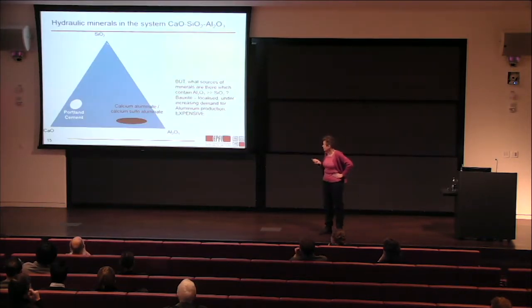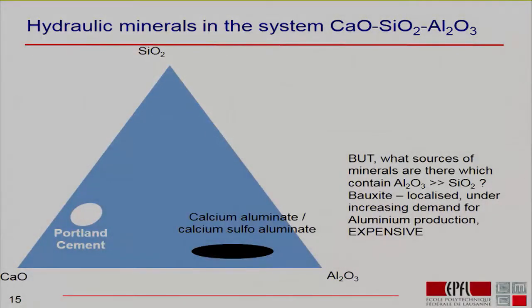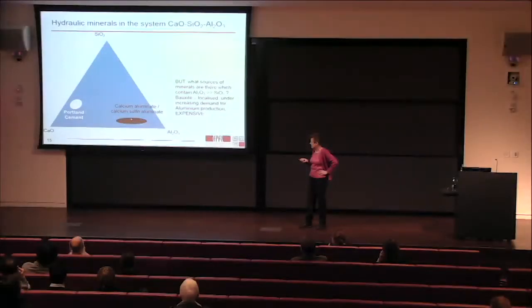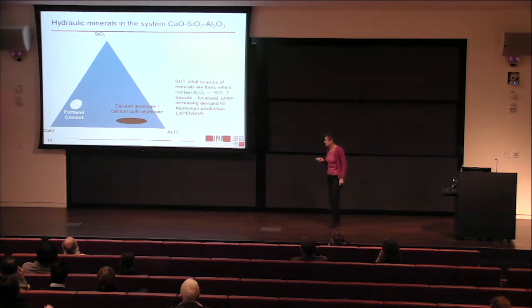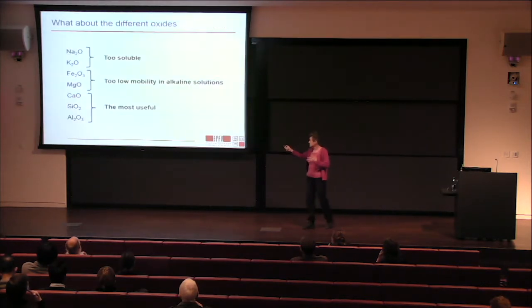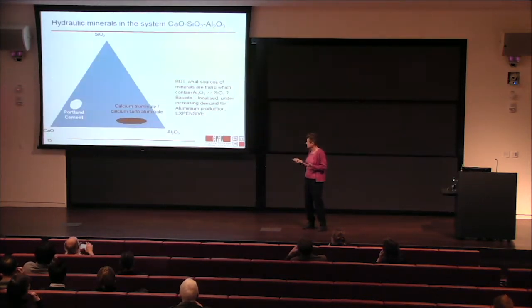And here, if we look at this system, calcium, alumina, silica, we see we've got the composition of Portland cements here, which are basically calcium silicates. The only other hydraulically reactive minerals we have in this system are down here, and this is basically calcium aluminate cements, and by extension, with a bit of sulfate in the system, calcium sulfoaluminate cements. Okay? So in this whole system of all the Earth's materials, these are the hydraulic minerals that are interesting. Of course, as I said, you can have barium silicates and everything like that, but that's not really serious.